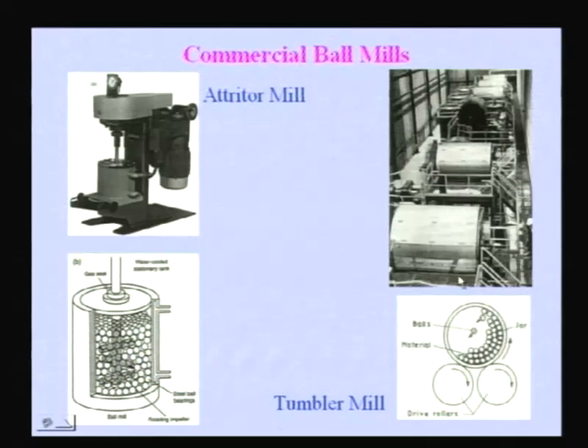So, you can see here a series of such tumbler mills. This is a picture from Inco Laboratories, International Nickel Company, USA, where they have really made commercial mechanically alloyed products from the elemental powders. All superalloys have been made in this kind of ball mills. So, here you can really have about 200 kilos without any problem. Only problem is whether the energies are high enough or not.